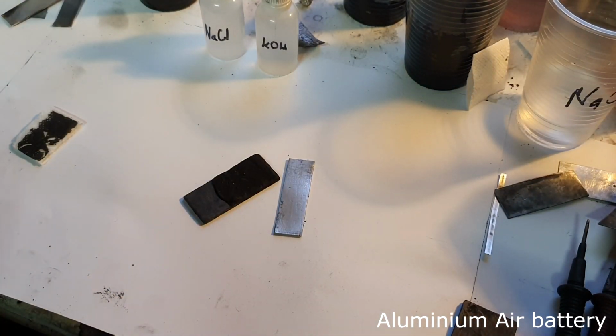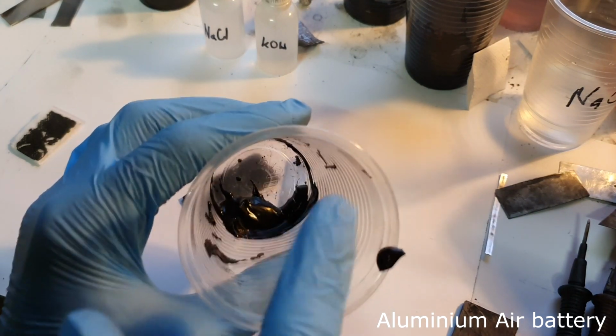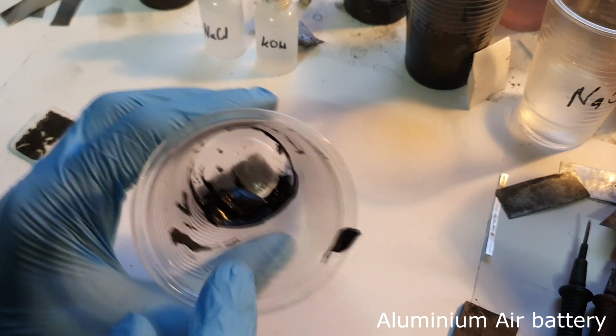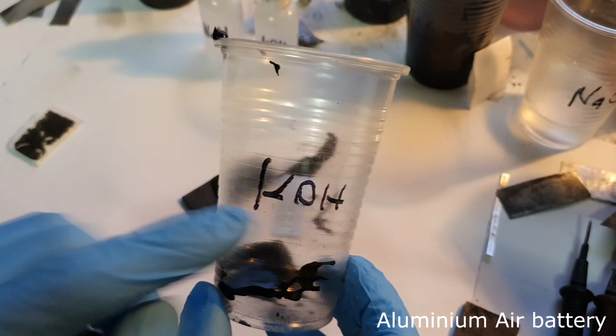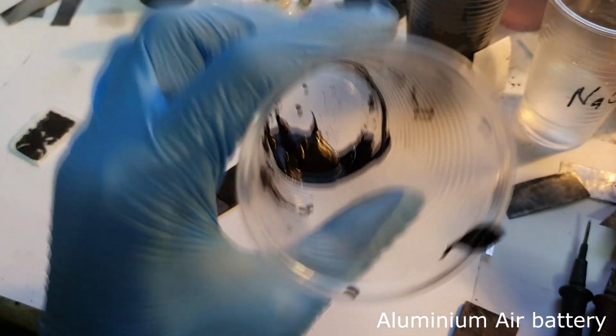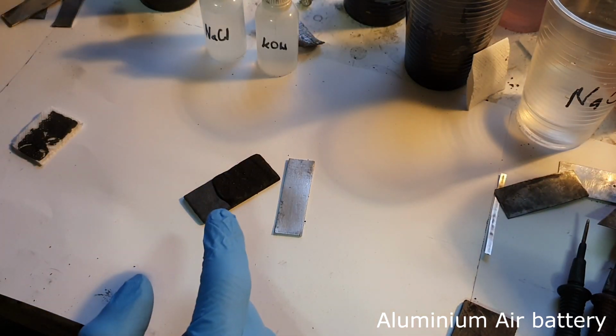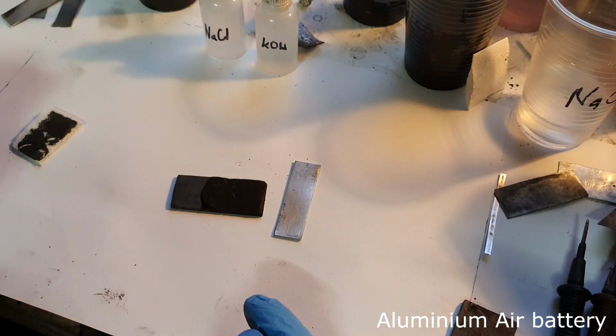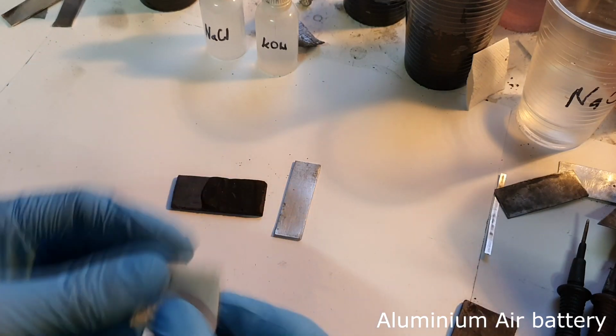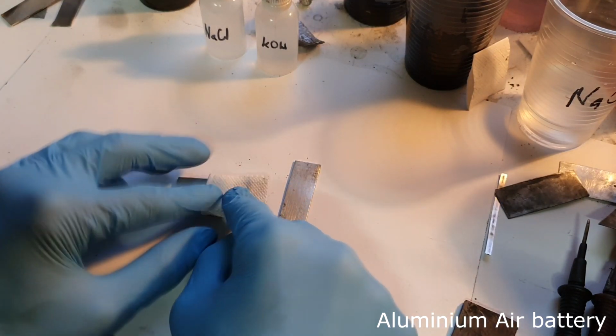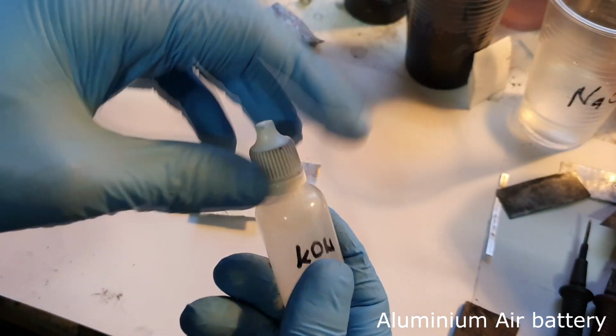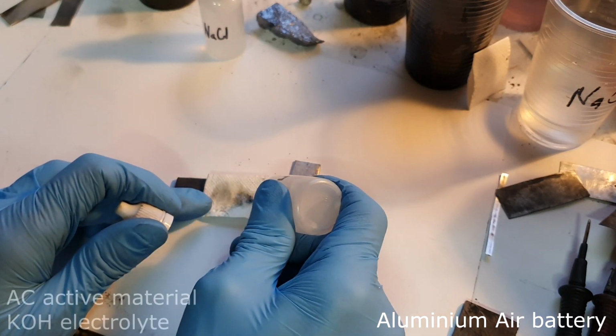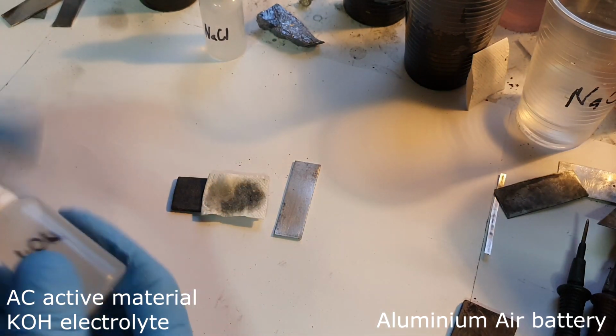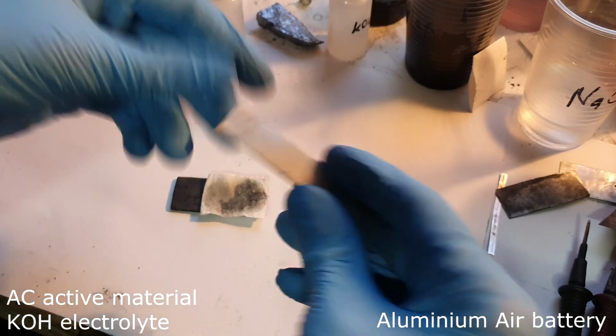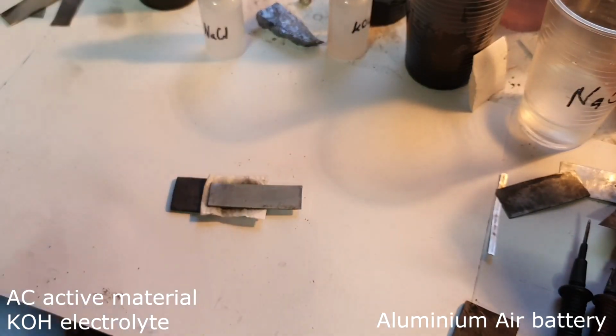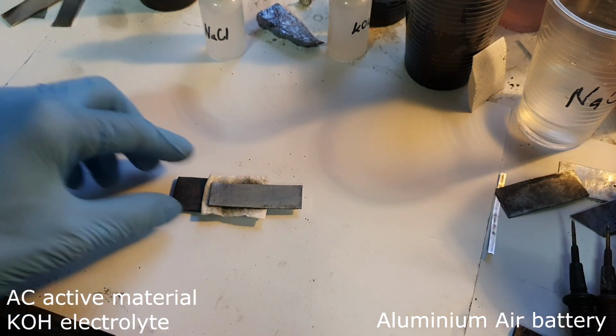So to prepare a slurry of activated carbon, I just add some activated carbon powder into this beaker, and on the top I put some of the electrolyte. In this case I use potassium hydroxide, and then I mix to get a slurry, and this slurry I put on my current collector, which in my case is a graphite plate. The separator of course is toilet paper. First I will use potassium hydroxide electrolyte. And aluminium on the top. And you get a really easily made aluminium air battery.